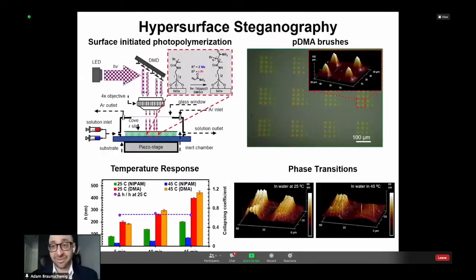Now, the last thing I want to tell you about before I tie this all back into how we can use this for mechanochemistry are results that I just got early this morning from a student in my group, Yurjan Zoldasov. And what we were interested in was stimuli responsive surfaces to create hidden images. So hidden images, it's an art called steganography that dates back all the way to the ancient Greeks. And the way that we sought to accomplish this was by creating films composed of a non-responsive polymer and a temperature responsive polymer that we would pattern side by side. So when you initially look at this film, all you see is a flat film, but upon heating above the LCST of the NIPAM, the NIPAM would collapse, revealing a hidden image.